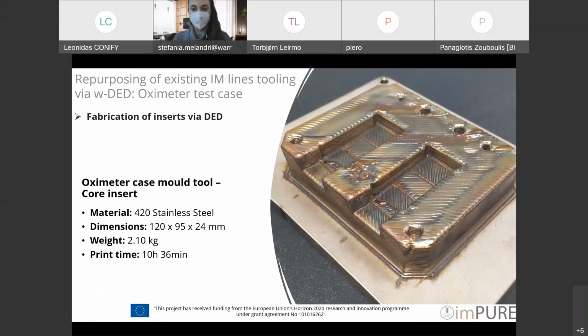So this is the oximeter case mold tool. Again, approximately 2 kilos, 10.5 hours. And you can see the different features and the holes. We achieved a good surface finish again, and a defect-free 3D printed part. So that was another big success story for us. So next slide, please.